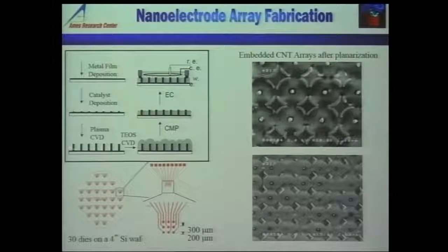And then we fill the gap between these nanofibers with silicon dioxide using TEOS CVD. Okay, so that serves two purposes. One is that you can get electrical isolation between the neighboring electrodes. The second thing also, during operation, it has got a mechanical robustness, so the nanotube actually doesn't fall down like grass on a rainy day. Okay, and so those are the two advantages. And then we do chemical mechanical polishing that exposes a tiny bit of carbon nanofiber. Okay, it's like the small whiskers on a teenager's face. The hair growth. So that's what it looks like.